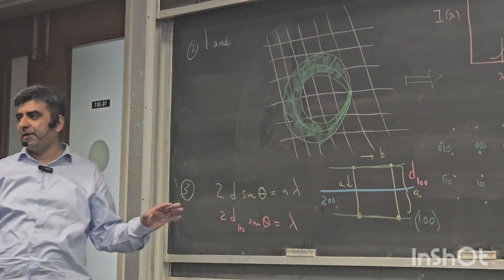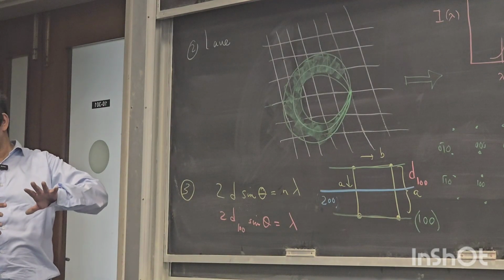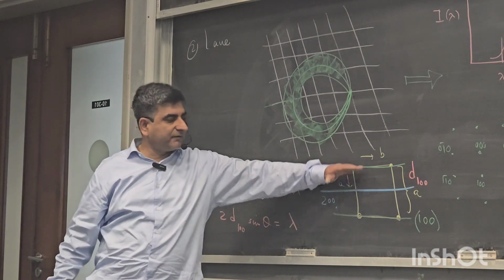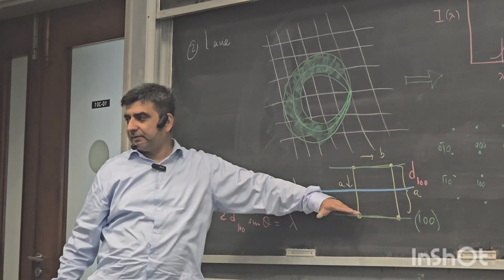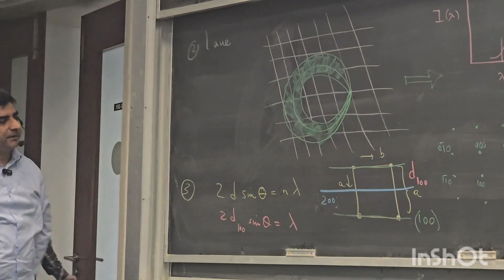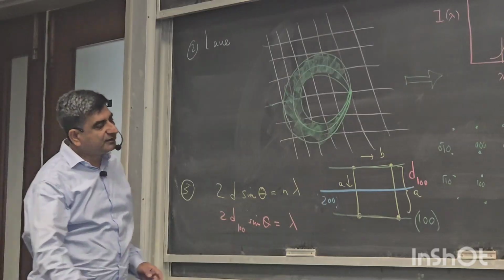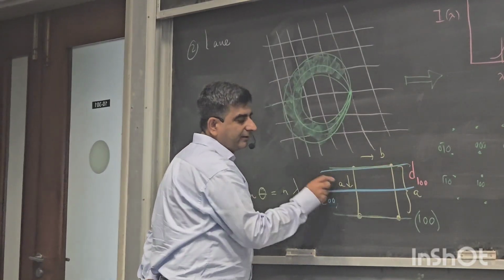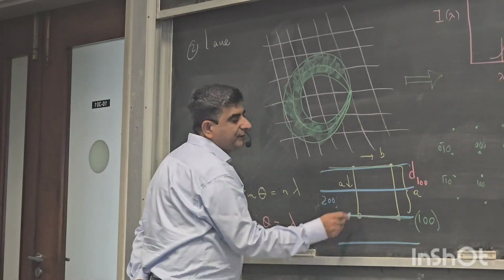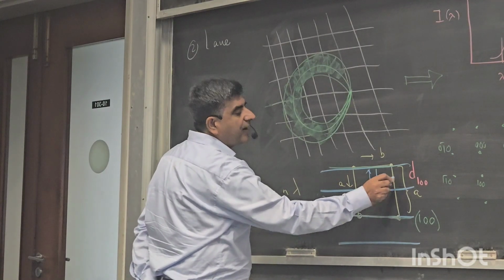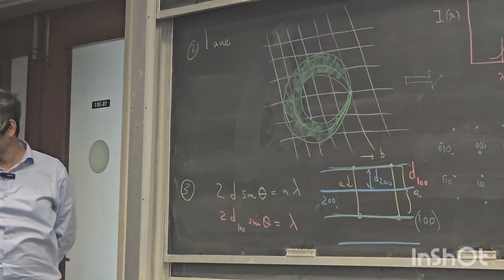It's halfway in between, and it's a primitive unit cell, so there are no atoms here. Everything has been defined with respect to these lattice planes. So I take this plane in between. The 2, 0, 0 planes are here, here, here, here. So the spacing between these planes, d 2, 0, 0, is half of d 1, 0, 0.